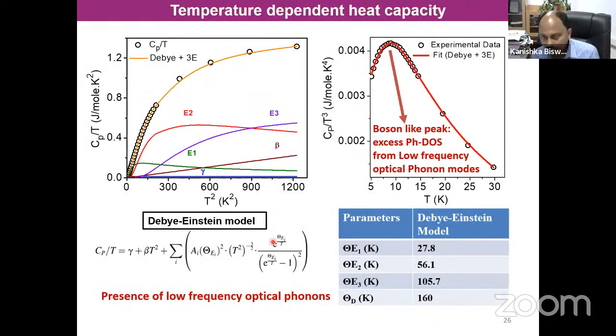So with that, we have measured the low temperature heat capacity to identify what is happening more in this system. And low temperature heat capacity is an indicator of many things. One thing I'll tell here: low temperature heat capacity data we cannot fit by the simple Debye model. So the Debye model is this, Cp by T versus T squared. If I take this T this side, so this is really the Debye T cube law, right? That we read in class in BSc. So this cannot be fitted by the simple Debye law. So we have to have Einstein modes, actually 3 Einstein modes, to fit this heat capacity data.